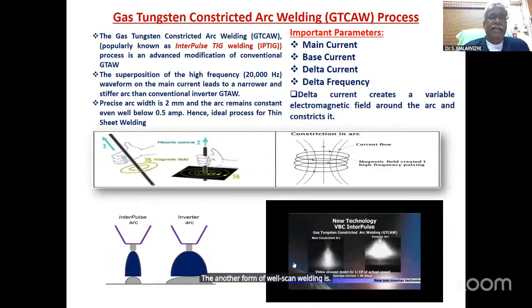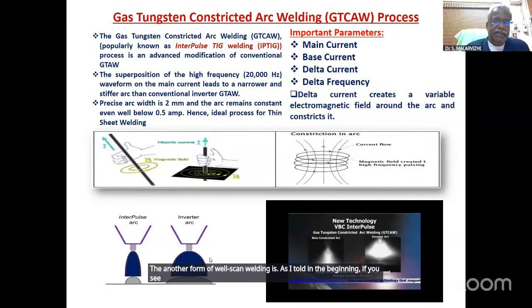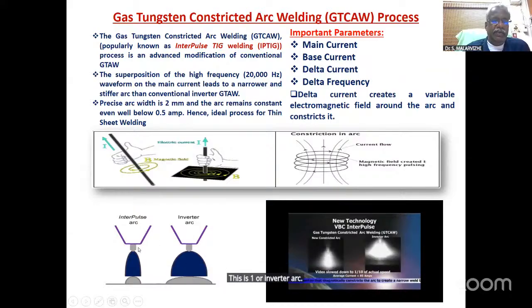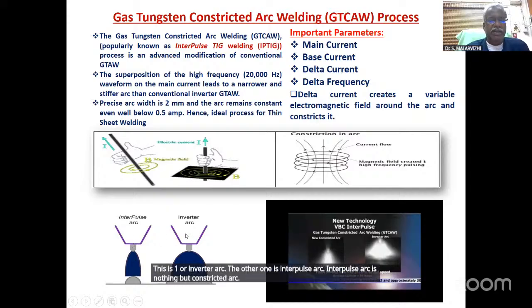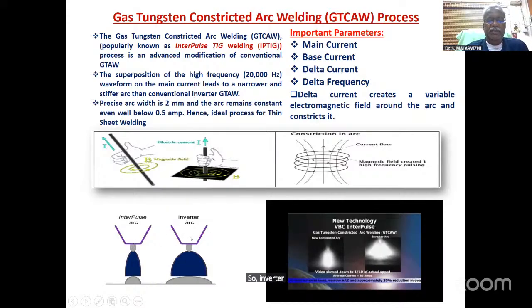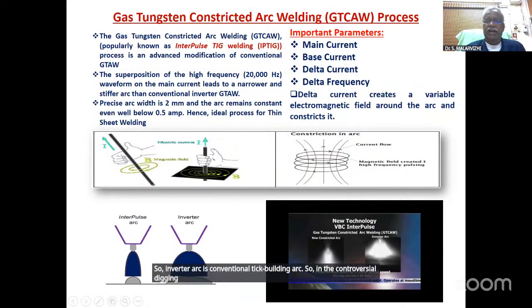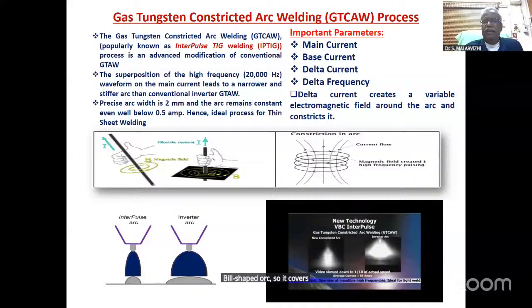Another form of pulse current welding is, as I told in the beginning, if you see this schematic diagram, one arc is the inverter arc. The other one is the interpulse arc. Interpulse arc is nothing but a constricted arc, gas tungsten constricted arc. The inverter arc is the conventional TIG welding arc. In conventional TIG welding, as I told earlier, the arc is a bell-shaped arc, so it covers a larger area. The heat supplied by the arc is distributed over the larger area.